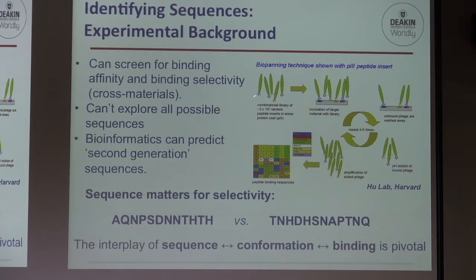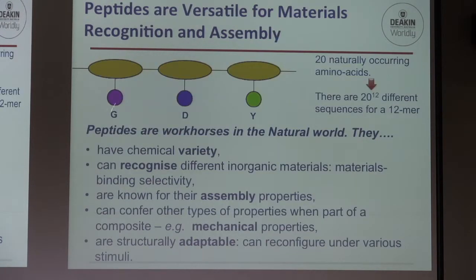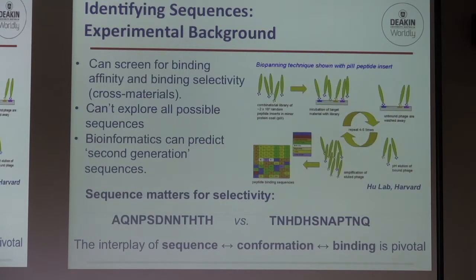So each of these peptides on each virus can be displaying a different sequence. That just means, maybe, these colours going in a different order. And so you can get a diversity of about a billion sequences in this kind of library of viruses. You expose them to different materials, you wash off the ones that don't stick, you keep the ones that do, and maybe go through that cycle a couple of times and then back out what that peptide sequence would be from the virus genome. And from that, you can figure out what sequences stick best to a given material.